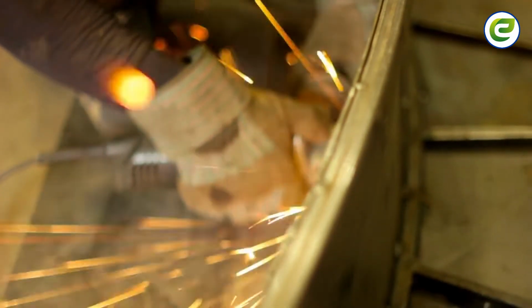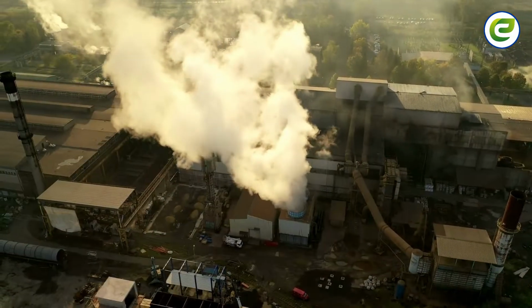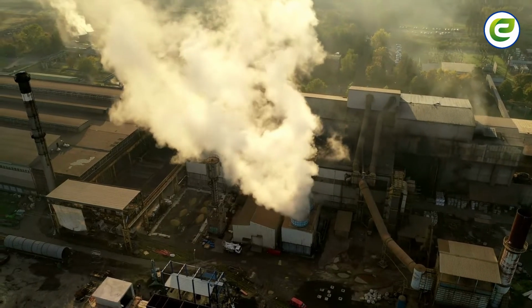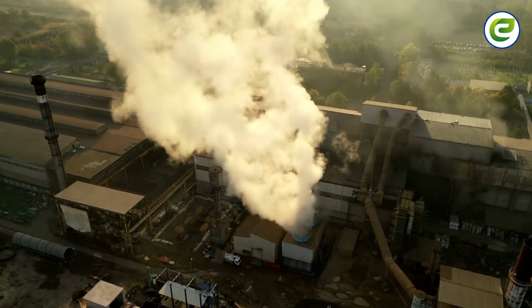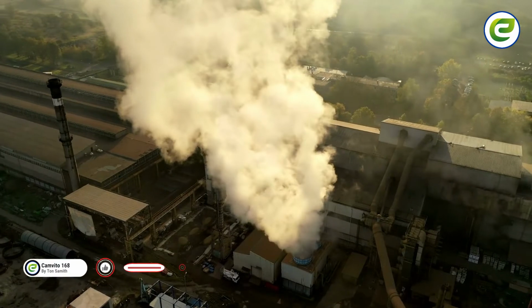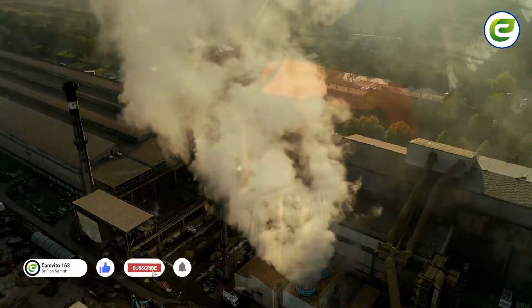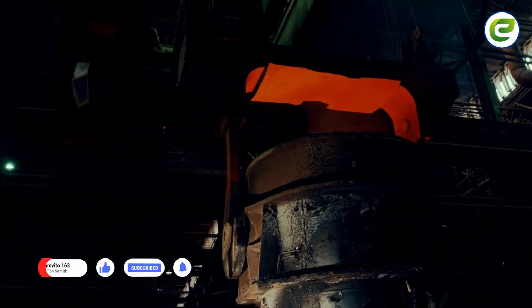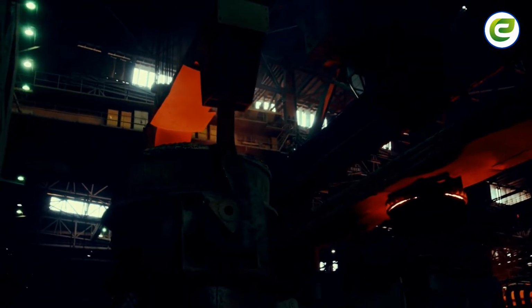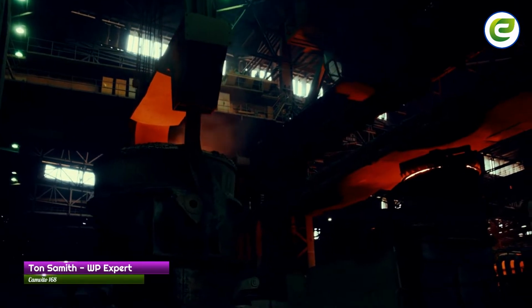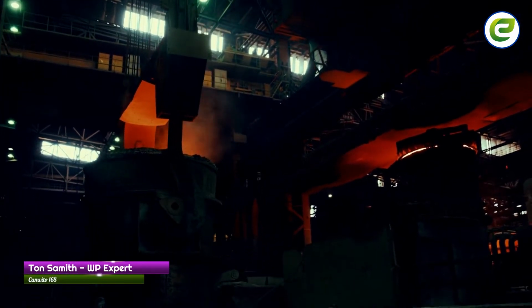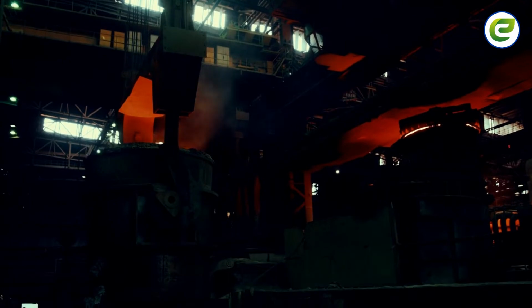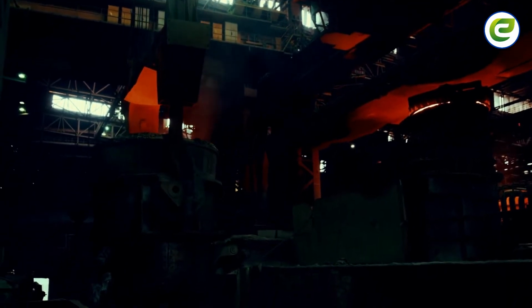The improvements were effected by increasing the manganese content to 1.5% and keeping the carbon content below 0.25%. A group of steels given the generic title high-strength low-alloy, HSLA, steels had the similar aim of improving the general properties of mild steels with small additions of alloying elements that would not greatly increase the cost. By 1962, the term microalloyed steel was introduced for mild steel compositions to which 0.01 to 0.05% niobium had been added. Similar steels were also produced containing vanadium.